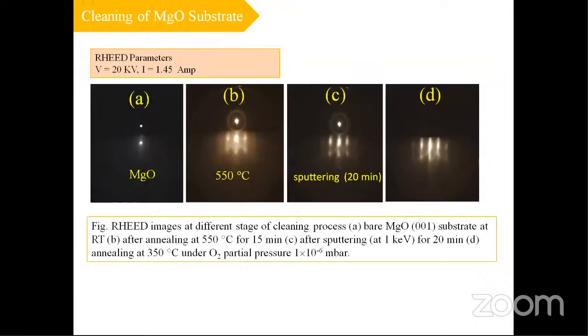Now, before depositing the Fe film on MgO substrate, first we have cleaned the MgO substrate. This is the RHEED image of bare MgO substrate. One can clearly see there is only one spot with a huge background, which confirms that the MgO surface is not clean. Now, to clean the surface, first we heated the sample at 550 degrees centigrade for 15 minutes. One can clearly observe that several spots have been observed.